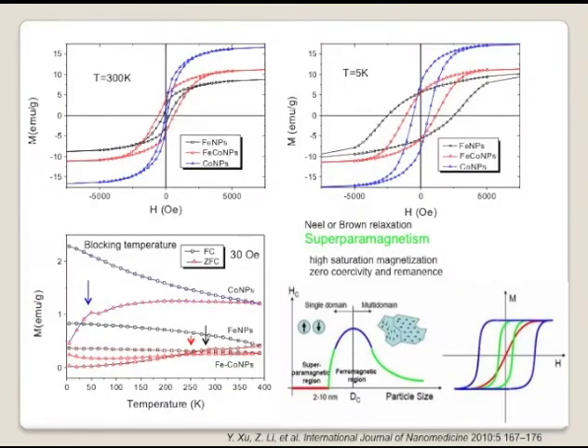Okay, let's do some magnetic property measurements for our nanoparticles. We measured the magnetization curve at a very low temperature, 5 K, and at room temperature, 300 Kelvin. We can see that our nanoparticle has a very high hysteresis loop, with a large area. We just said that a large hysteresis loop can generate more heat during the magnetization. At room temperature, this loop shrinks, particularly for cobalt nanoparticles. Almost nothing there. But they still have a high saturation magnetization.